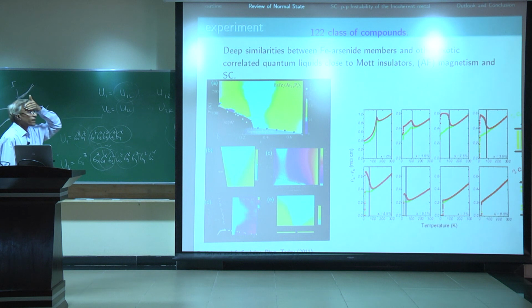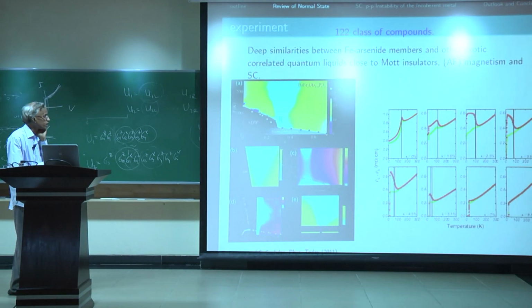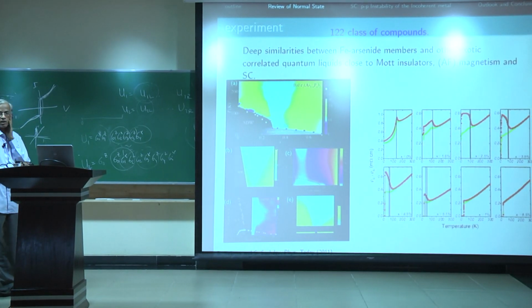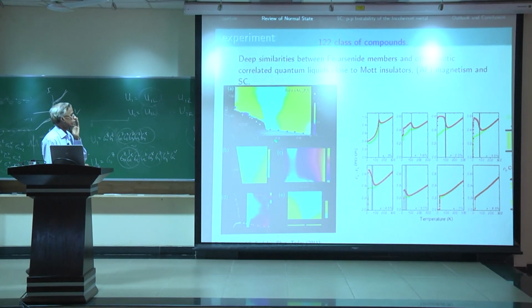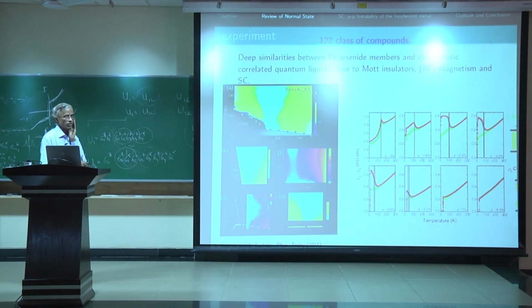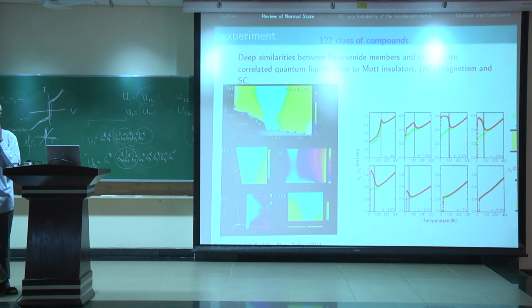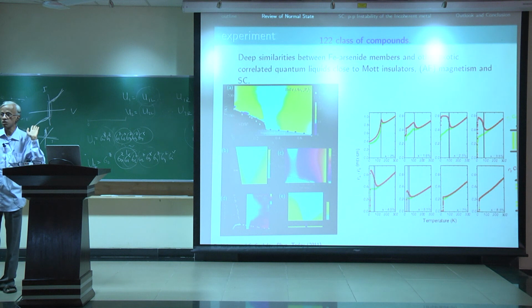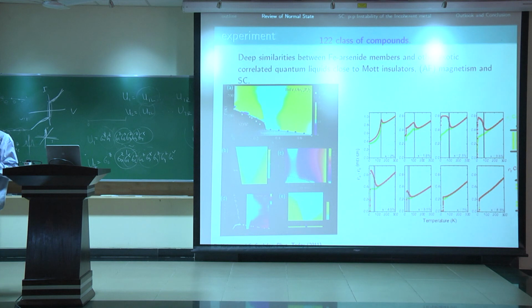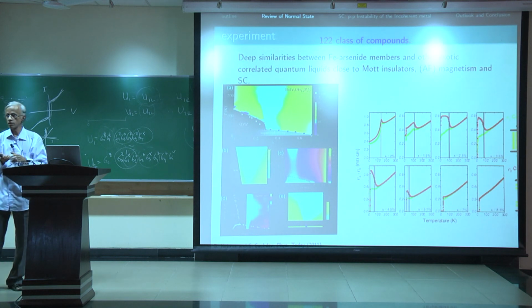An additional consequence of that is basically anomalous diamagnetism, most famously encountered in cuprates, and there is only one experimental paper which shows this in the iron arsenide context. But there is also additional work by Laura Green which basically says that as long as you are in the underdoped regime up to optimal doping, there is an excess Andreev current above TC, 40 Kelvin above TC, while when you cross the optimal doping, the excess current is gone. Okay. So that's the only thing one knows from tunneling. But as far as the symmetry is concerned, there is no data which questions the S plus minus.